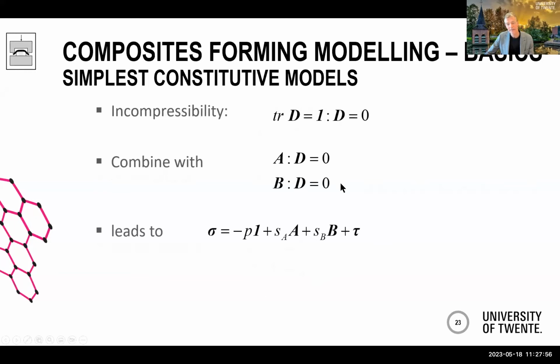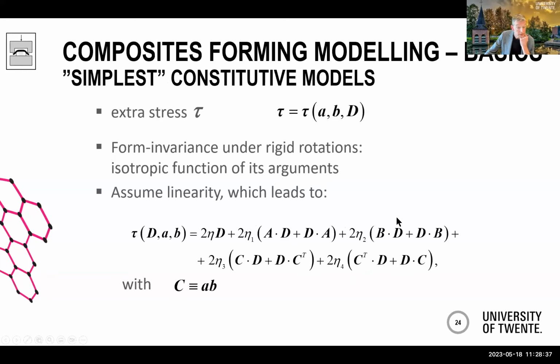So that means that we've got an extra stress in our total Cauchy stress plus 3 terms, something in the one direction, which reflects the incompressibility constraint, and something in the A and in the B direction. These 3 terms are not determined constitutively because there's zero strain in these directions, but these typically follow from the boundary conditions. So in this tau, the extra stress tensor, that's where the actual material behavior is hidden. Okay, and it's a function of these fiber orientations, A and B, and a function of the rate of deformation.